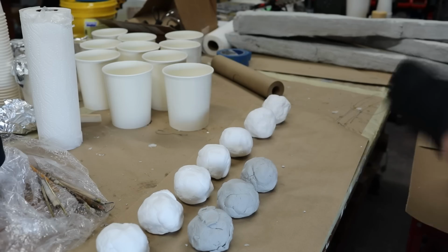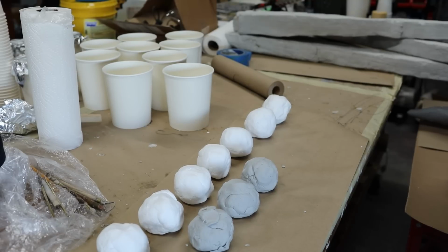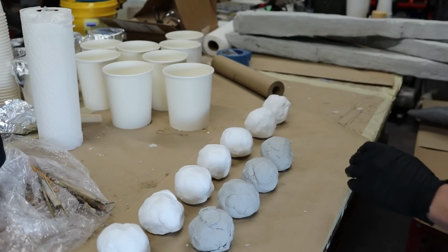So what we're using this material for in a mold making aspect, you can see in some sections there are big gaps. Even with the epoxy coat, there are big crevices where, when we lay fiberglass and resin on top of that, it's going to be impossible to get that glass tucked into that little nook, right?